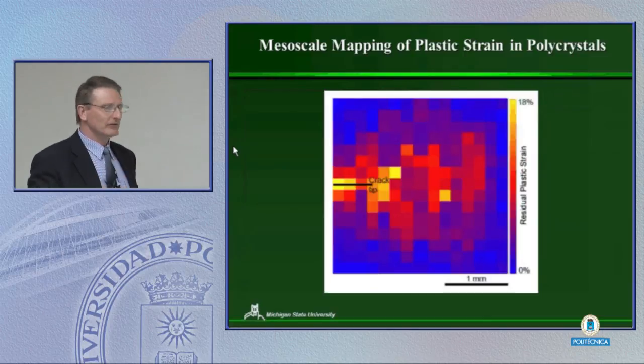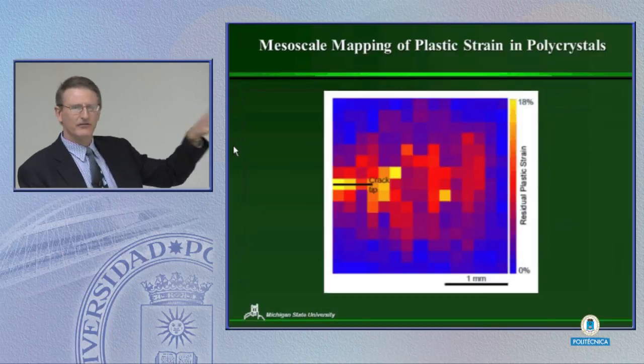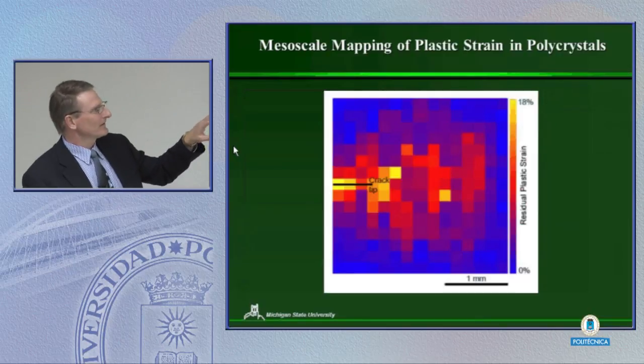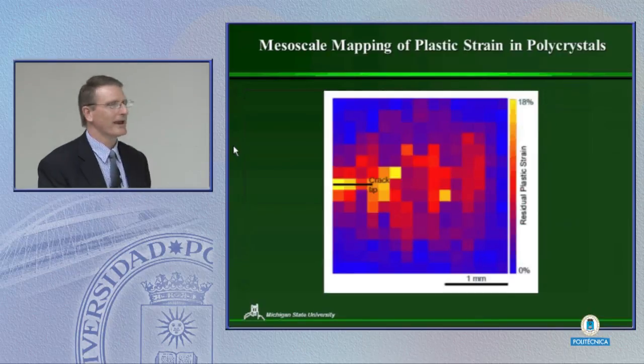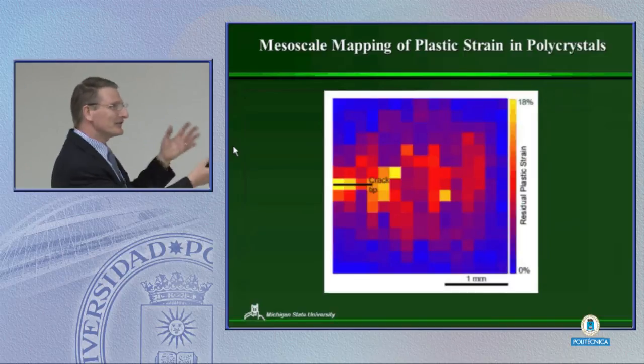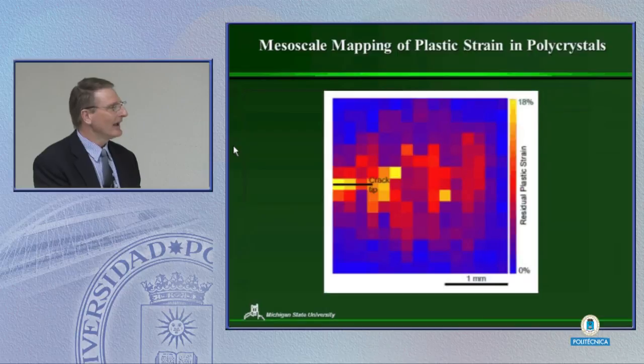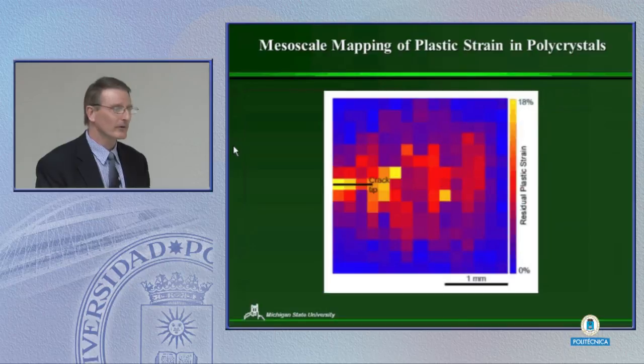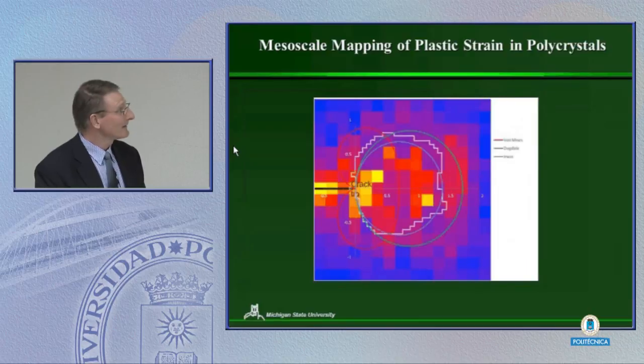Now, you know, I'm a microscopist, and everyone keeps working smaller and smaller, okay? But this is macroscopic. This is actually fairly easy to do. And, you know, like I said, I think maybe civil engineers appreciate this. When I show this to mechanical engineers, they get really excited because this is the scale they're interested in. And it was kind of amazing. As far as we could tell, no one had ever taken this kind of approach before. We recently published it in the Proceedings of the Royal Society, so they must have liked it. And we were able to go back and then make a comparison with the von Mises, the Dugdale, and the Irwin plastic zones. And we can see that it's actually pretty consistent.